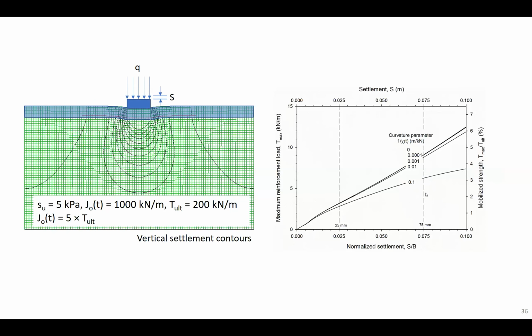From a practical point of view, what you see here is we have recognized that J is about 5 times T_ult, and this means that we can calculate what is the mobilized strength in that reinforcement. And you can see that the maximum mobilized strength is only about 6% of the ultimate strength. So this material, even though it's generating tensile load in the reinforcement itself, is not under a load level that would make us worry about whether it may fail in rupture.